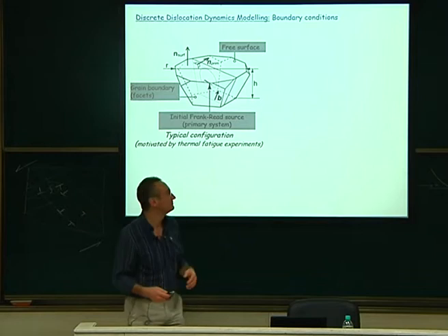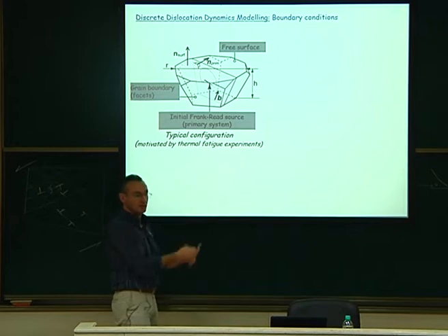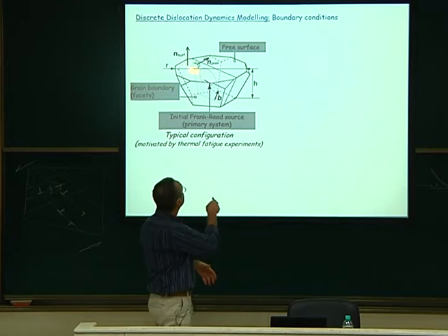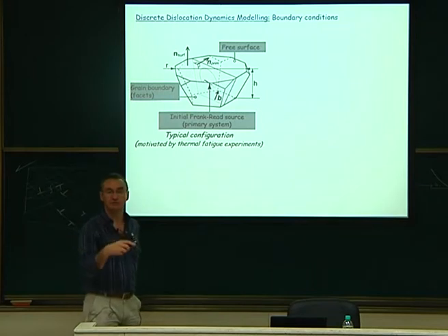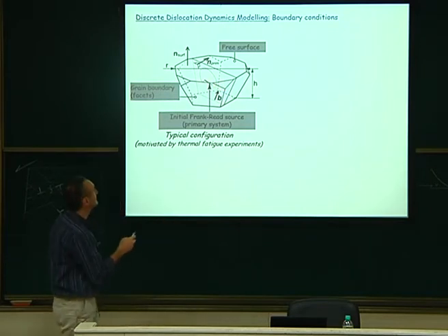It's not direct. First thing to do is we'll take a grain that is called a surface grain. It means that one of the surfaces of the grain is free. It's a free surface where the dislocations will go out, so that we hope to see the extrusion at that surface later on. Okay? So this is the top surface. Then we will put in that dislocation box, in the simulation volume, a dislocation source here. A single one, 8 or 7, one of the two that my colleague saw, with this Burgers vector. So either slip system number 7 or 8, and let them move.